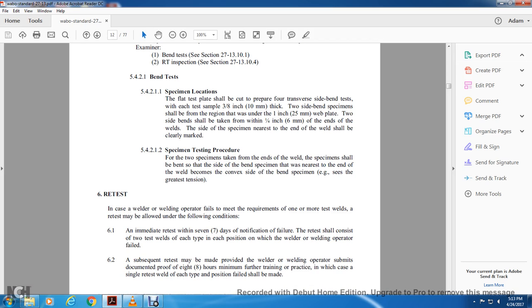5-4-2-1-2, specimen testing procedure. For the 2 specimens taken near the end of the weld, the specimen shall be bent so that the side of the bending specimen that was nearest the end of the weld becomes the convex side of the bending specimen, which sees the greatest tension.